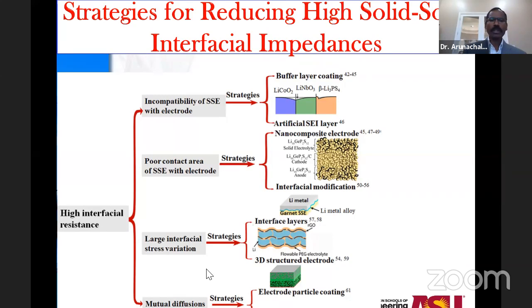And in terms of reducing the stress variations, you can have multiple components, including RGOs also. And it also says flowable PEG electrolyte. So that's again polymer, but you can have an extremely thin layer of other materials to make the surface a little more flexible. So you have the functional materials of all solid state components, anode, electrolyte, cathode, but in terms of reducing the stress or improving the structural stability, you could have components which are well known in the literature and very well understood, like RGOs and PEGs.